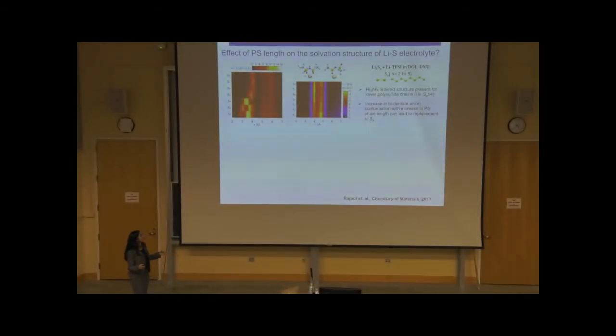The length of the polysulfide chain also plays an important role in controlling the dissolution of polysulfide species. And as I mentioned, there are different polysulfide chain lengths present in the solution. So we considered all the chain lengths from S2 to S8. And here you are looking at the radial distribution function of lithium-lithium as a function of polysulfide chain length. And we observed sharp peaks at smaller distance for smaller polysulfides, and by smaller polysulfides, I mean polysulfides less than S4. And as we increase the chain length of polysulfide, the peak intensity goes down and moves toward the right, which is again an indication that agglomeration is happening in shorter polysulfides as compared to longer polysulfides.